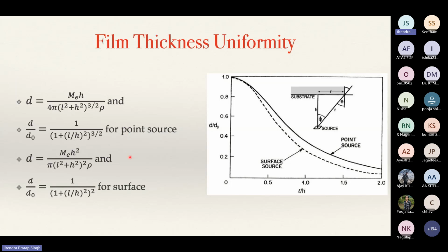So these are the two ratios, for the point source and for the extended source. If you plot the ratio of thickness to maximum thickness versus the ratio of the distance from the center to the height, you see the material deposited by the point source is comparatively more uniform than with the extended source. When L by H is 0, the maximum thickness will be at the center, and the thickness will vary as you move away from the center. That will always be the case, either with the point source or the extended source. But with the extended source, that variation is pretty sharp compared to the point source.